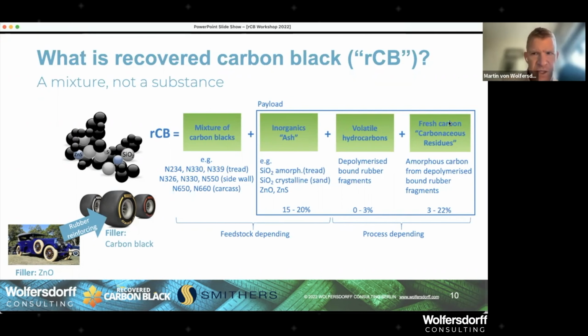Then we have fresh carbon, carbonaceous residues, and that comes from the carbonization of rubber polymer, the bound rubber around the carbon black. This is mostly amorphous carbon, although you could argue at higher temperatures there might be some graphitization happening. So amorphous carbon from the depolymerized bound rubber fragments. And this could be anything between 3 and 22%. In fact, this is very much depending on the feedstock and the type of carbon black as well.